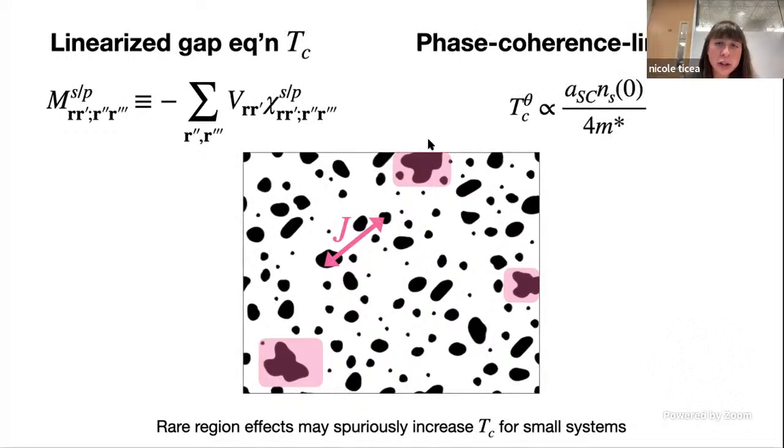The corresponding resistance of the state will drop to 0 only when the islands become phase coherent, which sets another temperature scale for the problem, which I call T_C theta. You can solve for this transition temperature by assuming that the only degrees of freedom in your problem are the phases on each island, which admits a description of the system as an XY model. And it's really the helicity modulus of the XY model that's equal to the superfluid density, which can be calculated